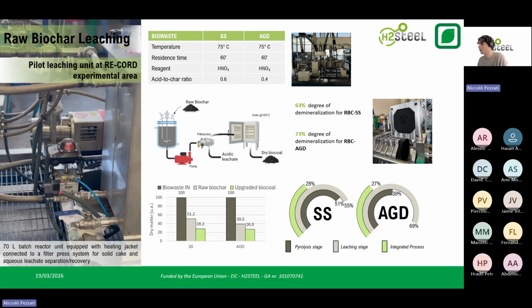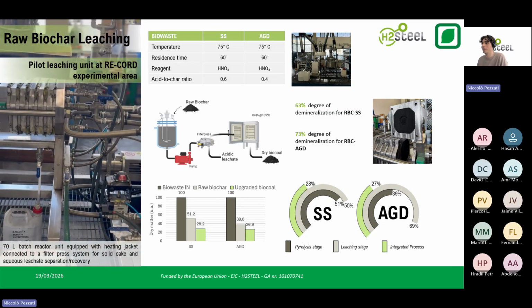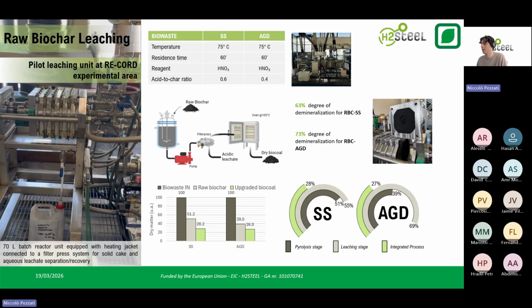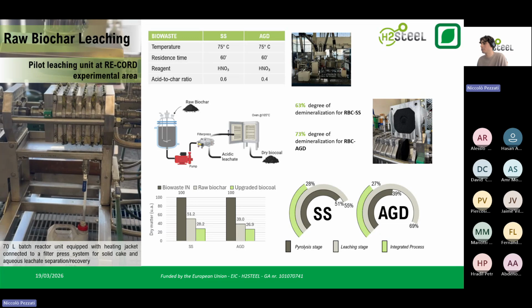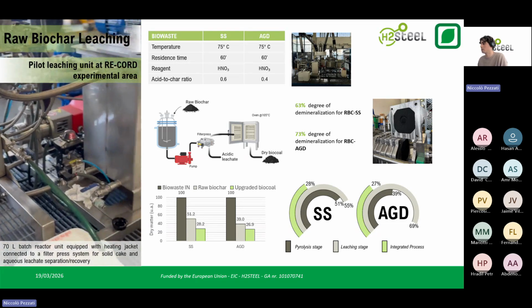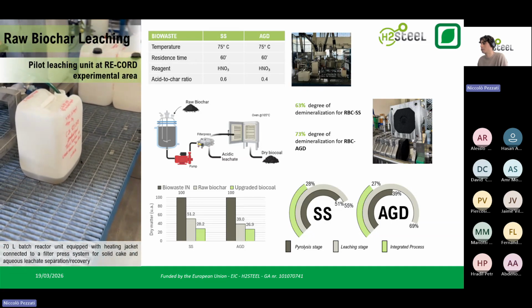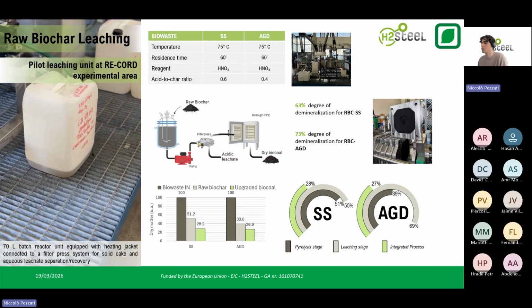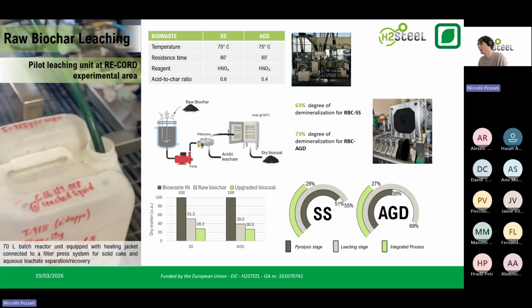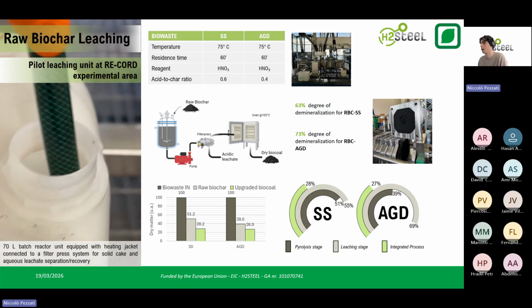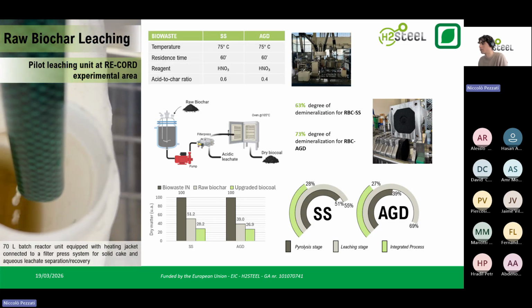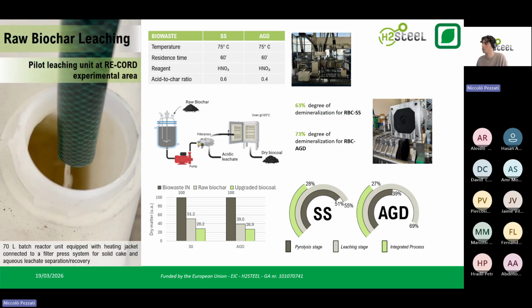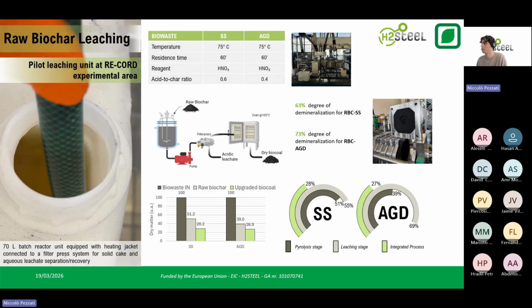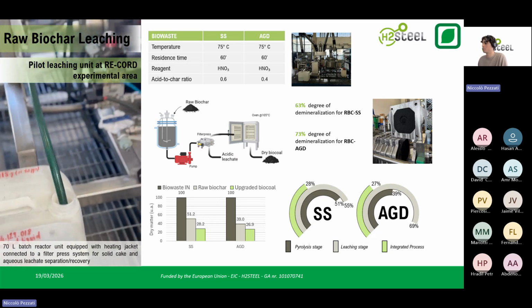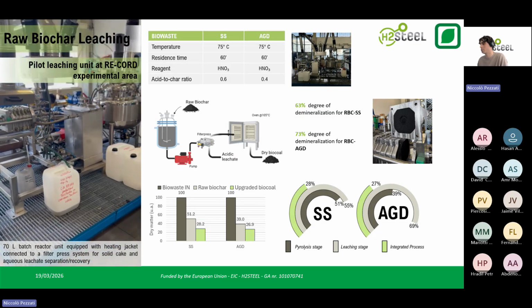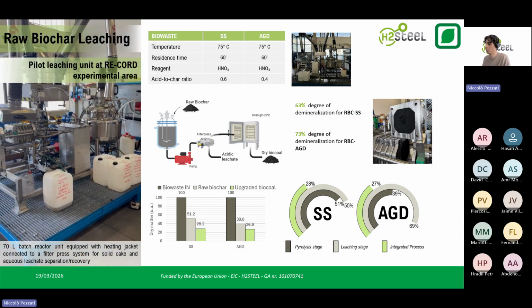And all in all, we reported the yields of the integrated process. So first, the pyrolysis stage gives a 51% solid yield when treating the sewage sludge and a 39% solid yield when treating the agricultural digestate. Then the leaching post-treatment has a solid yield of 55% when treating the raw biochar from the sewage sludge and 69% solid yield when treating the raw biochar from the agricultural digestates. And eventually we have respectively a 28% solid yield and a 27% solid yield for the overall process.